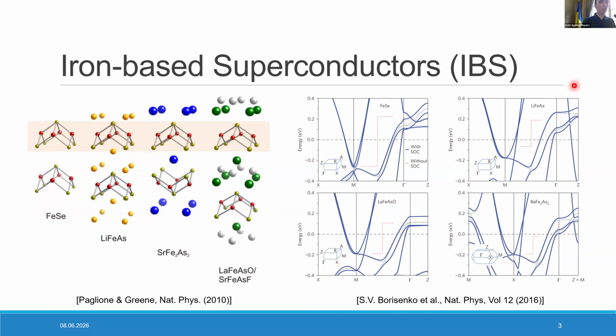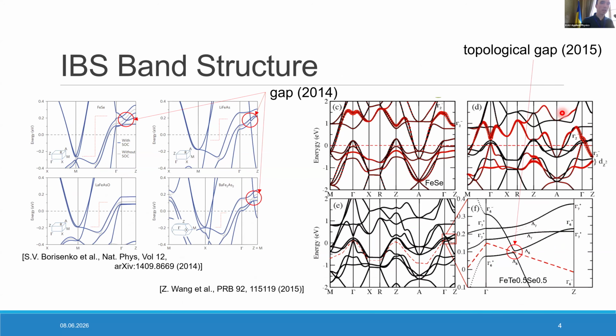Maybe not as complicated as platinum bismuth 2, but still a multi-band system with many bands crossing the Fermi level. In 2014, it was shown for the first time that the spin-orbit induced hybridization of pnictogen or chalcogen p bands and iron d bands opens a gap, and quite fast after that, in 2015, it was shown that this gap is expected to be inverted, which means that the surface states that emerge in it are topological surface states. So this logically brought a lot of attention to this class of materials.